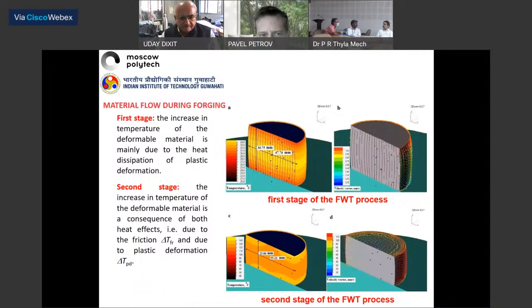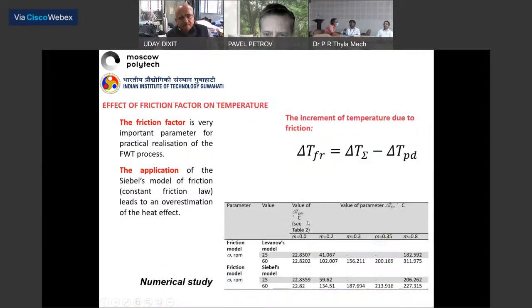Such kinematics of the material flow follows a very huge release of heat in the thin layer of material which is close to the contact surface. Due to that, as a result, the increase in temperature could be up to 200 degrees if we talk about the plastic deformation of aluminum alloys. Let's compare: the increase in temperature due to the heat effect of plastic deformation during the first stage is not more than 40 degrees centigrade. But during the second stage, the temperature could increase up to roughly 200 degrees.